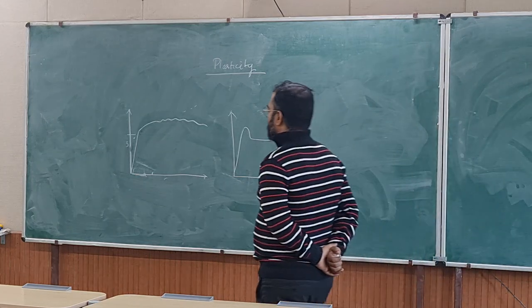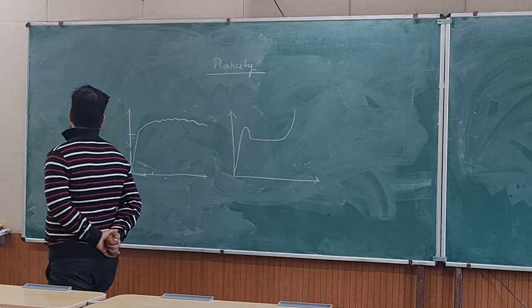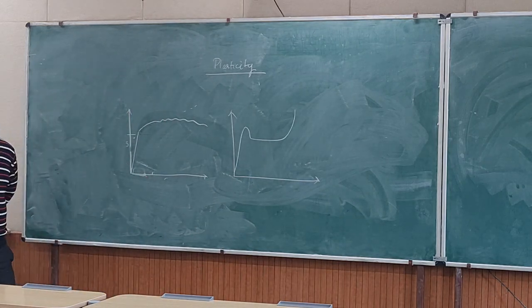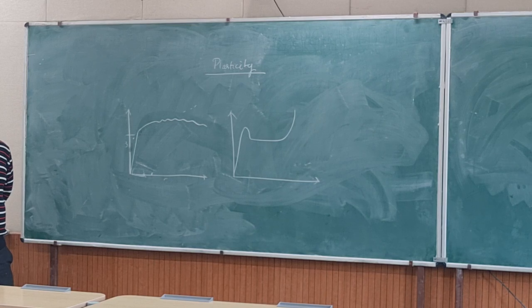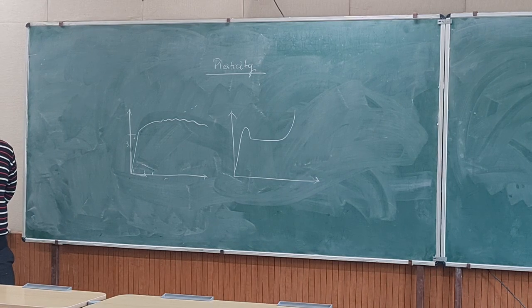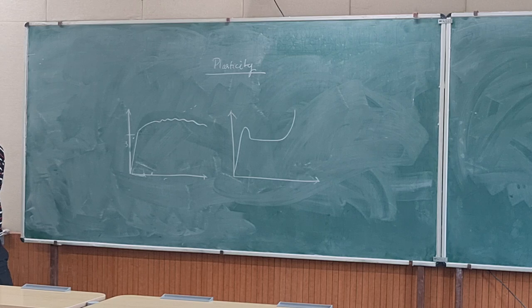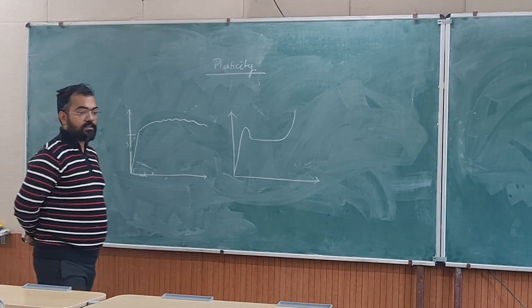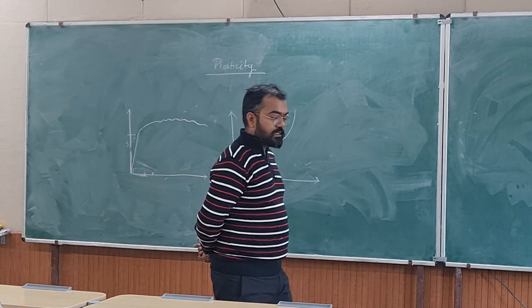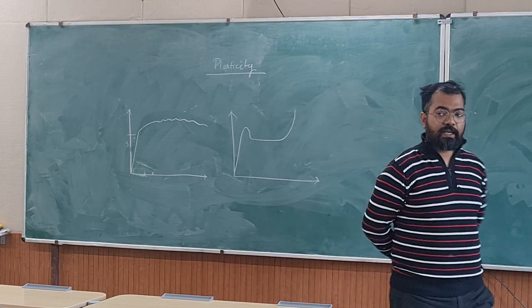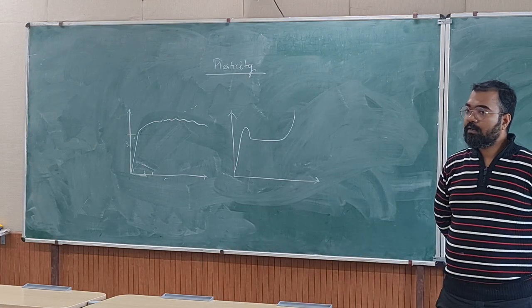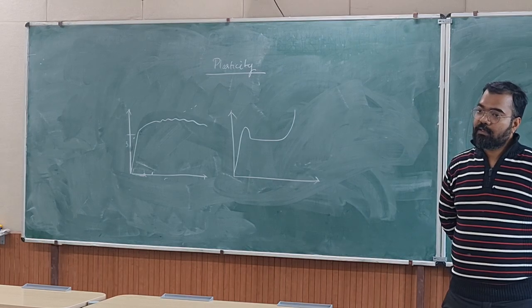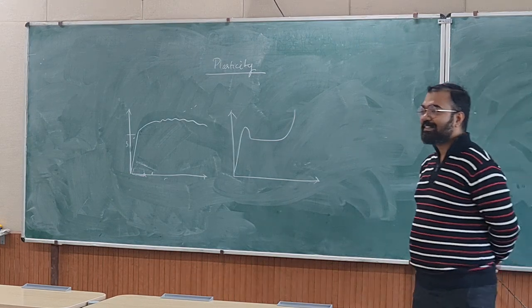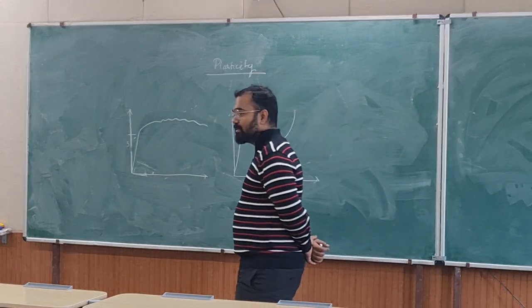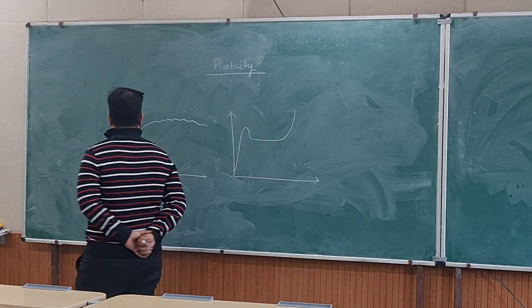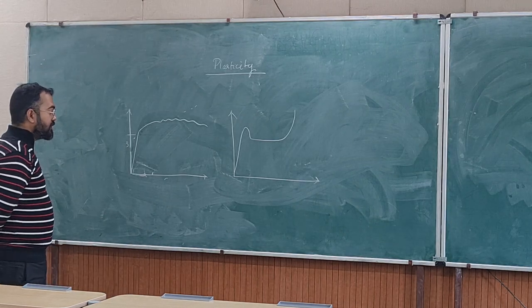So there are some known reasons for this, and a special case is what is known as yield point phenomena. That's a special case which happens because of interstitials locking the dislocation, and it doesn't happen by substitutional atoms because interstitials are like motor bikes on the road. They can also go on the footpath and kill someone and move ahead. So they have a very high diffusion coefficient. Their diffusivity is good.